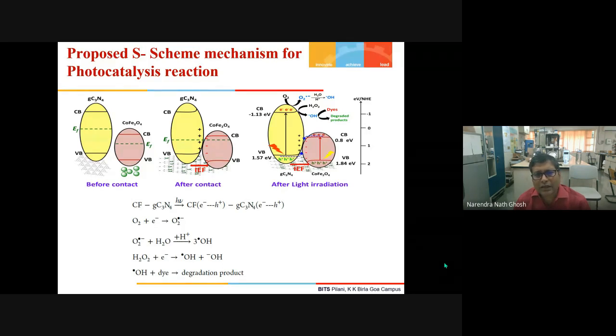And in the conduction band of graphitic carbon nitride, the hydrogen peroxide and oxygen produce the radicals. H2O2 directly forms OH dot, O2 first forms O2 dot minus, and then that species reacts with water and H plus to form OH dot. And these OH dot cause the dye degradation.